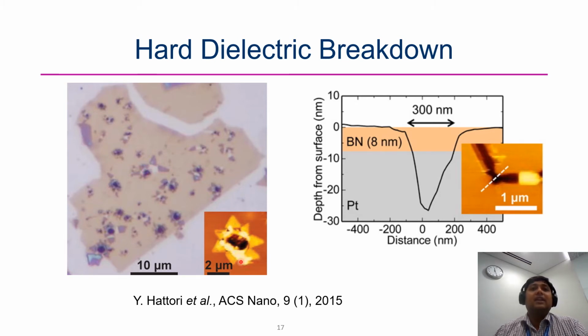You can see that in the topography image there is a deep pit created. Whenever the dielectric breakdown happens, especially hard breakdown, people found that there is a very large pit formed in the hBN. There is a drastic material removal happening, and this can also be seen, for example, in this 8 nanometer hBN, where we have a 300 nanometer wide pore formed at the breakdown spot.